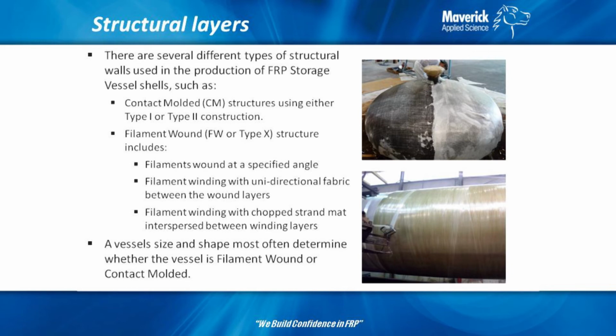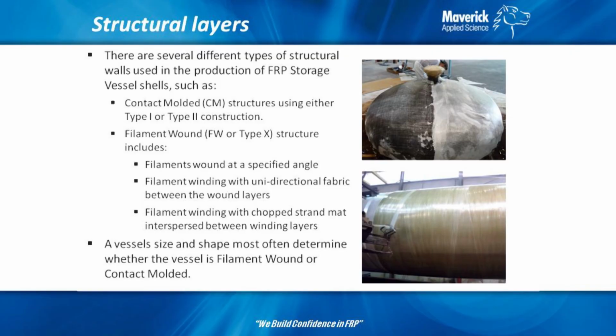So contact molded structures have a much higher content of resin in them. For instance, paper mills recommended using contact molded piping for years and years because the corrosion resistance of that piping was thought to be higher, because there's a higher resin content in that pipe.